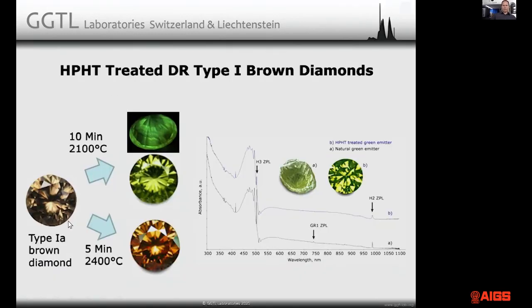HPHT treatment: you take a brown diamond to start with. You heat treat it for a couple of minutes at 2,100 degrees, a deformation-related brown diamond. It'll turn greenish yellow, with strong green fluorescence, like what we all know as a green emitter diamond. If you take the same diamond and treat it at 2,400 degrees instead of 2,100 for a couple of minutes, the stone will turn orange or vivid yellow without any fluorescence. So what are you doing? At the lower temperature, you're destroying the vacancy clusters, and you're creating strong H3 center absorption and luminescence.